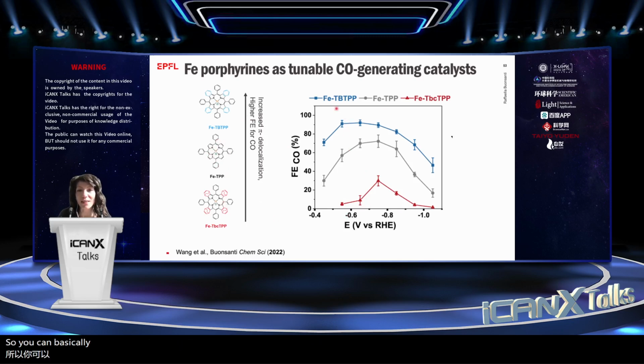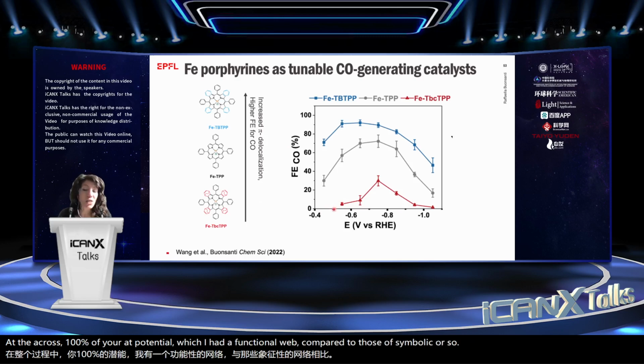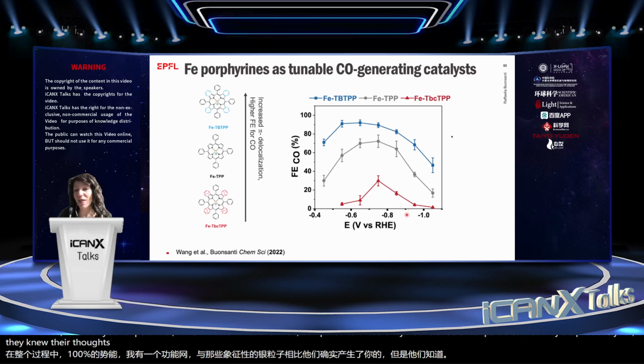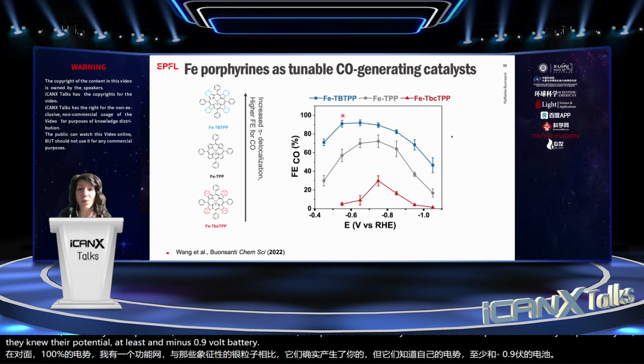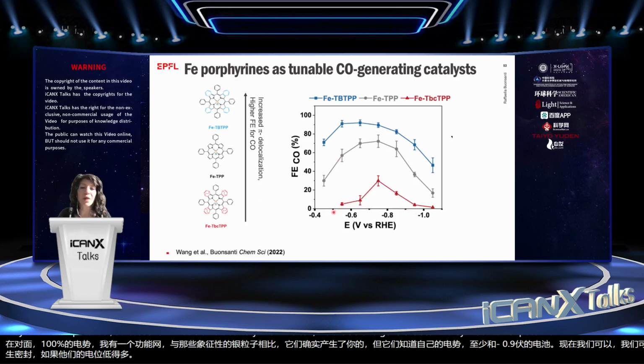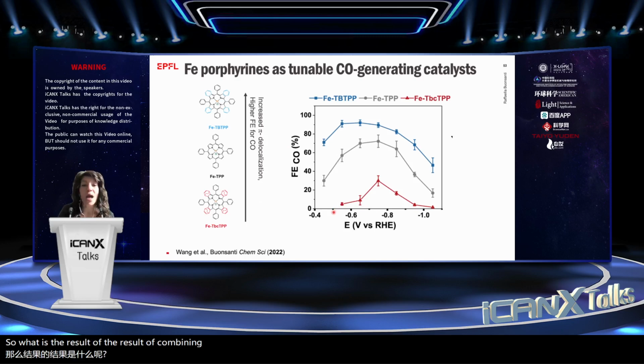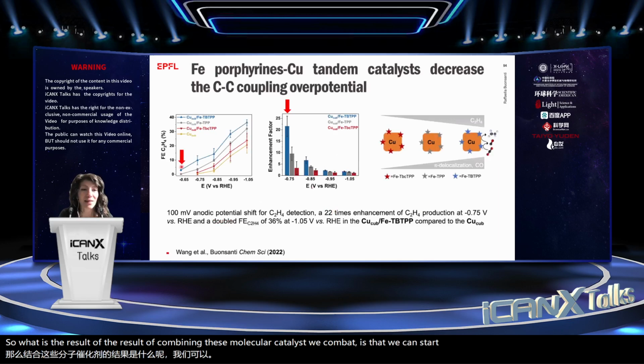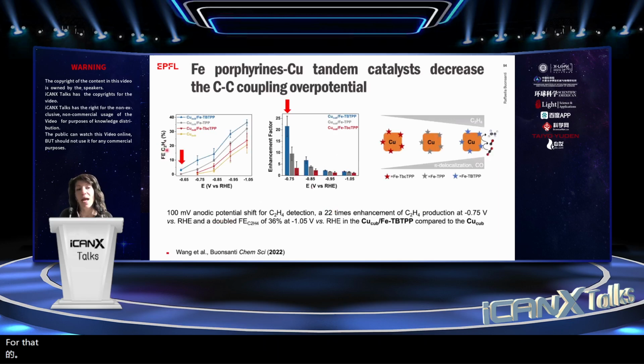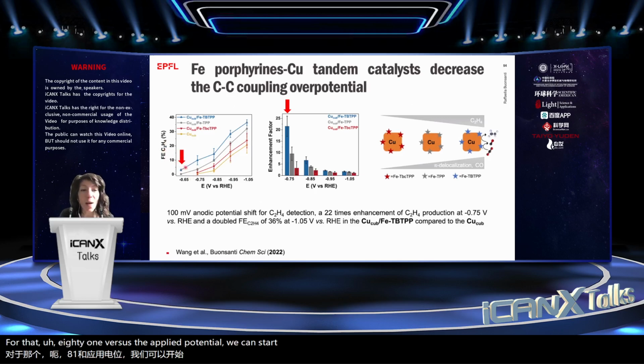So with this iron TBTPP, you can get close to 100% of CO at potentials which are much lower compared to those of silver particles. Silver particles do produce CO, but they need a potential of at least minus 0.9 volt versus RHE. Now we are able to generate CO at a much lower potential. So what is the result of this? The result of combining this molecular catalyst with copper is that, if we look at the Faradaic efficiency for ethylene versus the applied potential, we can start to appreciate ethylene at potentials which are much lower than the potential at which we can start to detect ethylene for copper cubes.